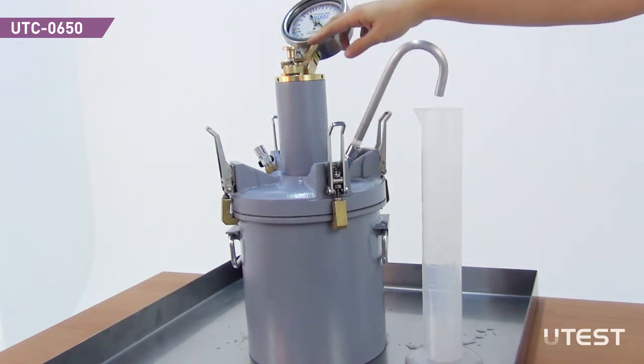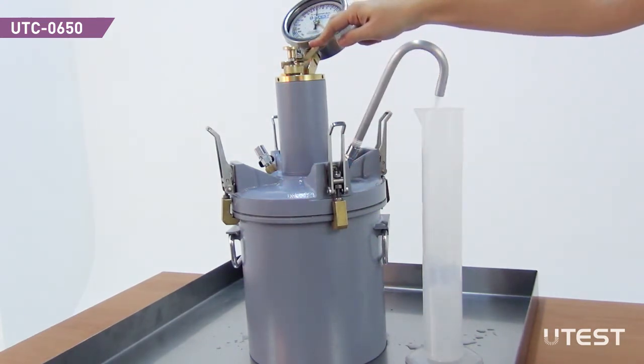Remove water from the assembly by opening the petcock with the J-tube attached and cracking the air valve. The amount of water corresponds to the desired calibration percentage.